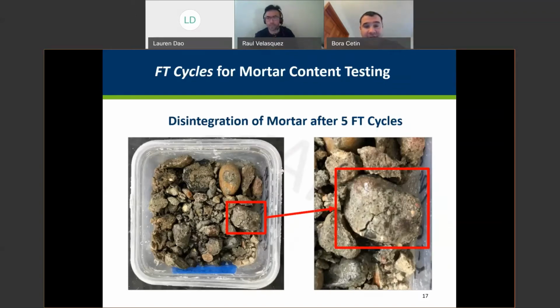But one thing, after 5 freeze-thaw cycles, when we were determining the mortar content of the RCA materials, as you can see, this large particle that's supposed to be aggregate had a huge mortar attached to its surface, and once it is exposed to the 5 freezing and thawing cycles, it develops a huge crack, indicating that the RCAs will disintegrate when they are exposed to freeze and thaw cycles. How much this will impact in the long run is one of the questions. In the short term, in the 2-3 years, it didn't impact the stiffness significantly, but we may want to see such an effect in the long term, but we don't know it yet. After freeze-thaw cycles, it is very clear that the mortar is being disintegrated. All right, Raul.